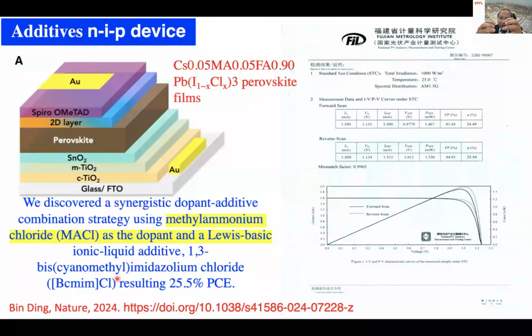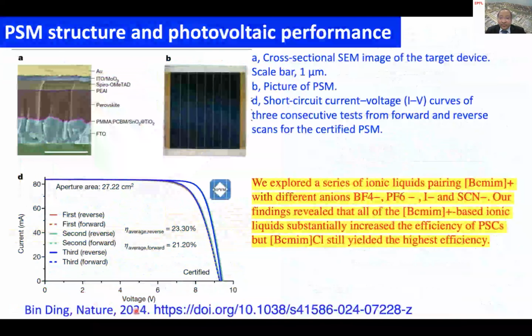When you mix the lead iodide and organic halide compound, they instantaneously form a three-dimensional structure. So here, by incorporating the methylammonium chloride, we slow down the crystallization process. What does it mean to slow down the crystallization process? When you slow down the crystallization process, you reduce the defects, and reducing defects gives you high voltage and power conversion efficiency, which gave us 25.5% efficiency. This work appeared in Nature last year. And this is the module efficiency, the mini module.